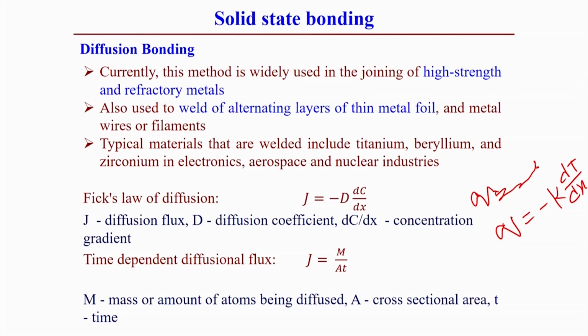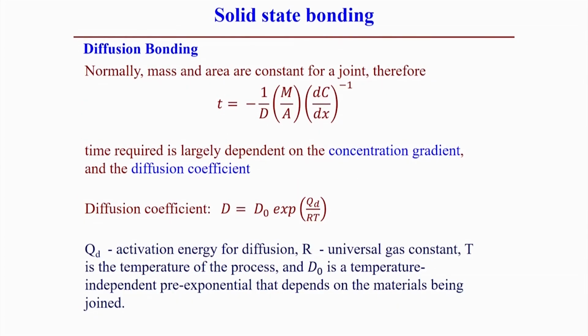So from these two equations we can find that the time requirement for the diffusion bonding of the two samples can also be estimated, that is, minus 1 by D, m by A, and 1 by dC by dx. So basically the time requirement is inversely proportional to the diffusion coefficient and the concentration gradient. If the diffusion coefficient is very high, the time requirement will be less, and at the same time if the concentration gradient is very high, then the time requirement for the bonding will also be less.